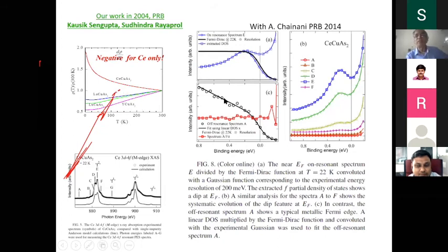We have established, for example, by a tunneling experiment, that if you look at the density of states at the Fermi level as a function of photon energy, there is a dip here. It is called a pseudogap. This pseudogap dip is responsible for the negative temperature coefficient of resistivity. They are all very exotic things. Today, one is trying to understand the origin of the insulating behavior in this material, because there are theories which suggest a hybridization gap.